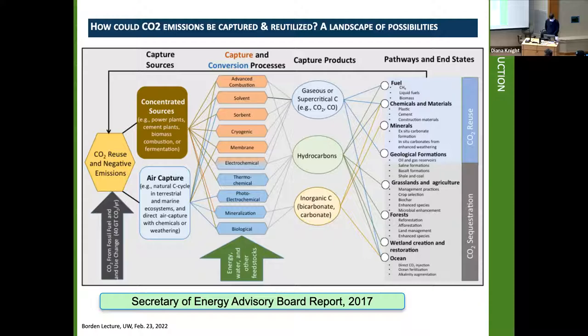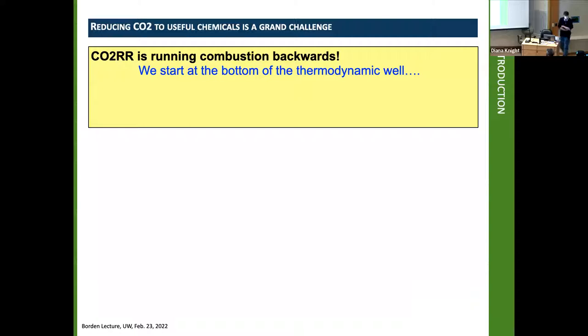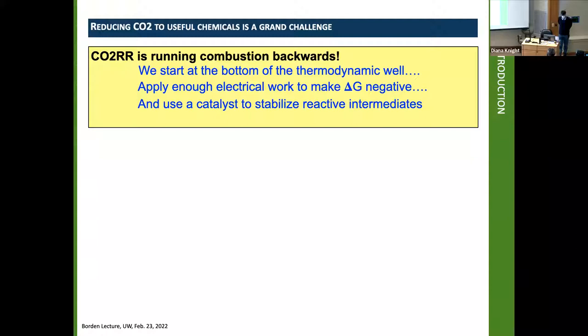So let's begin thinking about why this is so difficult. Essentially, we're trying to run combustion backwards. In other words, we begin at the very bottom of a deep thermodynamic well, and we want to lift ourselves out of it with energy, with solar energy, or at least energy that derives from solar photons. We need to do enough electrical work with green electricity to make delta G negative to convert CO2 into, for argument's sake, biobutanol. And we then need to use a catalyst of some kind to stabilize the reactive intermediates and of course to make the kinetics possible. So altogether, this is a very difficult challenge. We're trying to do non-spontaneous chemistry.